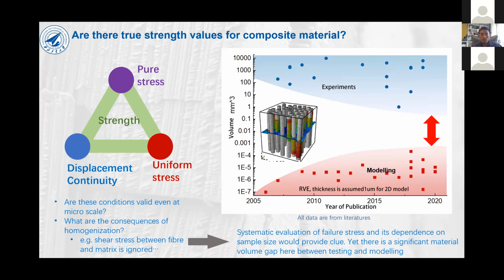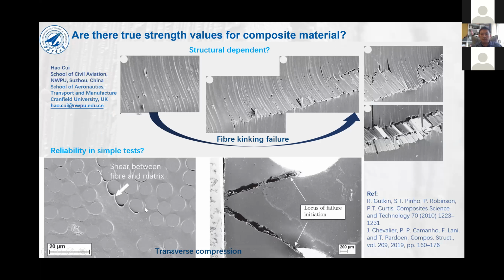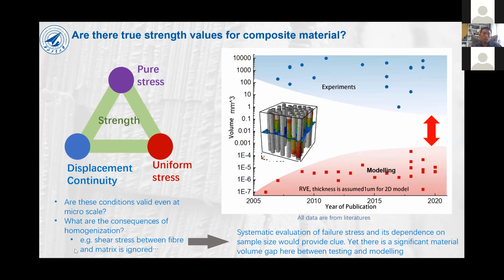So what are the consequences of this homogenization? First of all, we have ignored the edge effect at this small scale. For example, we cannot account for the shear or any other secondary stress at the edge. And the thing is, how do we get a better idea about the consequence of the homogenization when we start from a single fiber and a matrix to a unidirectional lamina, and further to a multi-directional laminate, where we can even consider it as quasi-isotropic? So what are the consequences and what are the errors involved in this whole process?